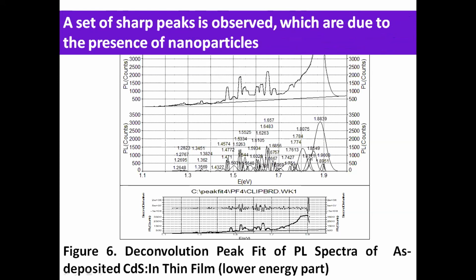Now, as you see, the sharp peaks, when fitted, give doublets here, doublet, etc. We see doublets everywhere. These doublets are related to the presence of two phases in the films, the cubic one and the hexagonal one, where they are separated in energy by about 6 to 7 milli-electron volt.